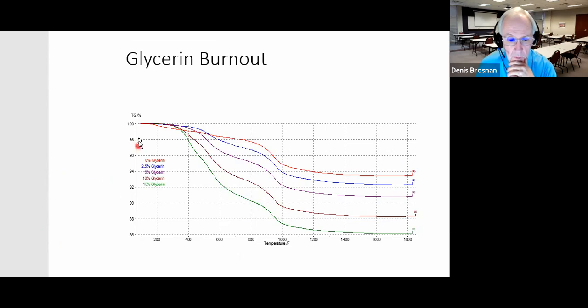Just to mention, we also did some glycerin burnout curves just to try to see what was happening at the low temperature region. So you can see that glycerin was coming out likely over a range of temperatures due to depolymerization up to about 1,000 degrees. So some of these complex binders take a while to remove by evaporation, depolymerization, or oxidation.